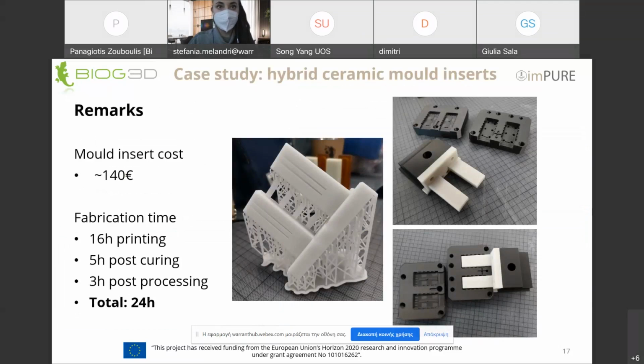So some remarks and some pictures here. We produced this part, the white part on all three pictures, the double insert, the side core insert. It is a component that costs around 140 euros, and the fabrication time is, as you can see, 16 hours to print, 5 hours to post-cure, and 3 hours to post-process afterwards, leading to a total of 24 hours.